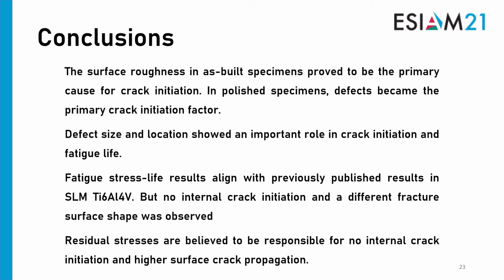The conclusion taken for as-built specimens manufactured by selective laser melting is that the obtained surface roughness was proved to be the primary cause of crack initiation and resultant fatigue life. When the specimens were polished, a higher life was obtained and the defects became the primary crack initiation factor. The defect size and its location showed an important role in the crack initiation and the resultant fatigue life.